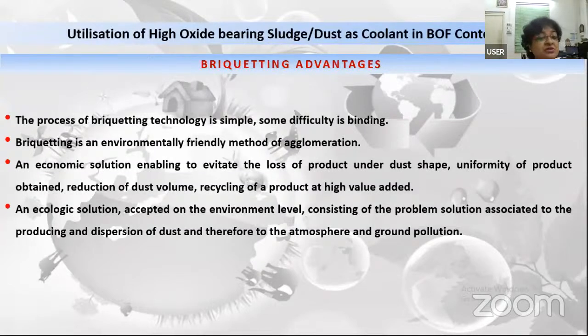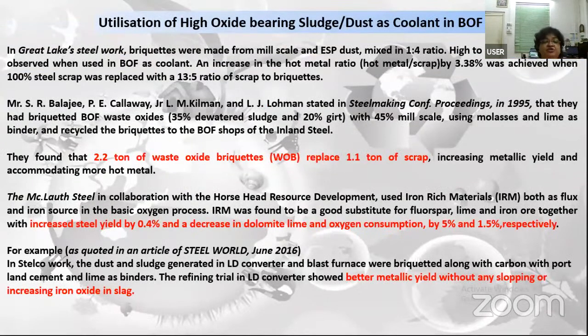And what is the environmental solution? The environmental problem is associated with the production and dispersion of dust. It solves that problem, and therefore it gives a good atmosphere, and ground pollution is reduced. Now see, which company has adopted this particular technology? At Great Lakes Steelworks, briquettes were made from mill scale and ESP dust mixed in a 1:4 ratio, and high to medium slopping was observed when used in BOF as coolant. There was an increase in the hot metal ratio by 3.38%, and 100% steel scrap was replaced with a 13:5 ratio of scrap to briquette. So this is the advantage.